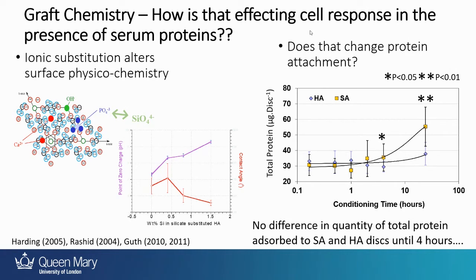So we looked at the protein absorption, and again found that there was no actual difference in the amount of proteins being absorbed to the surface of our materials until we got to 24 hours. So when you implant something, and when you look at cell attachment, all of that's happening instantly. So a difference not happening until 24 hours couldn't really explain why we were getting a difference in cell attachment in a couple of minutes.